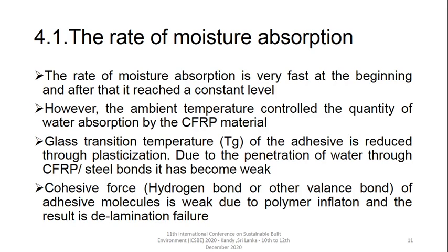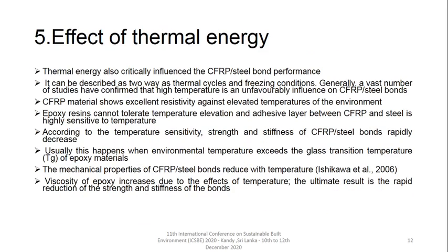Glass transition temperature, Tg, of the adhesive is reduced through plasticization. Due to the penetration of water through the CFRP-steel bond, it has become weak. Cohesive force, hydrogen bonds or other valence bonds of adhesive molecules are weakened due to polymer inflation, and the result is delamination failure.